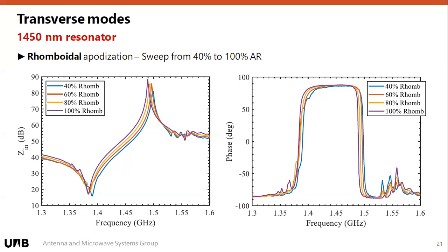The resonator should be, out of band, a capacitance, so you should have minus 90 degrees. And in between the resonances, you have an inductive behavior, so you should see a plus 90 degree phase. So we can see here for a 40% apodization, okay, we have cleaned the modes in terms of the impedance curve. We don't see them, but if you look at the phase, we still have some ripples here. If we go up in apodization, we see that we get cleaner and cleaner, but notice that we somehow are starting to lose a little bit of coupling.